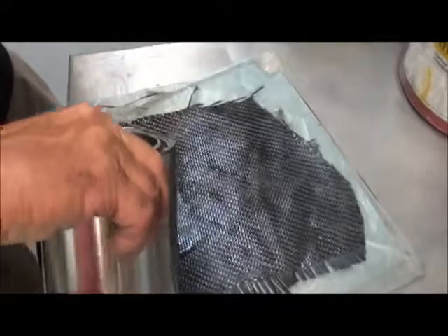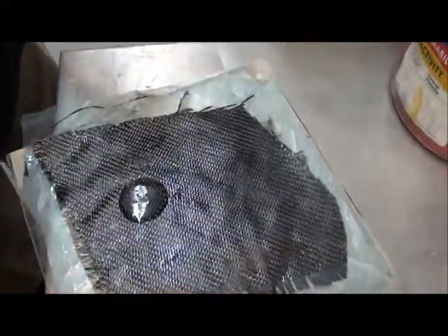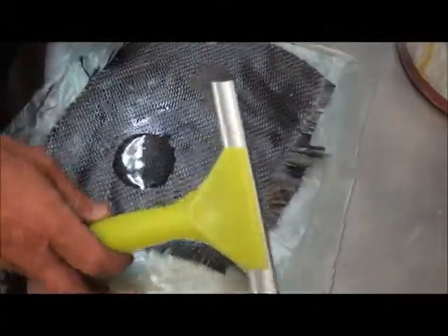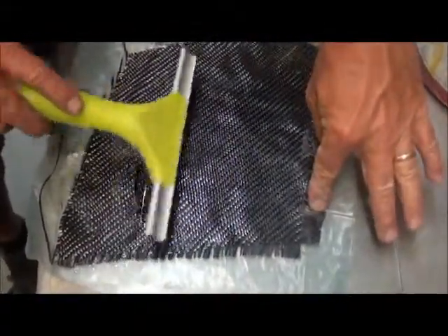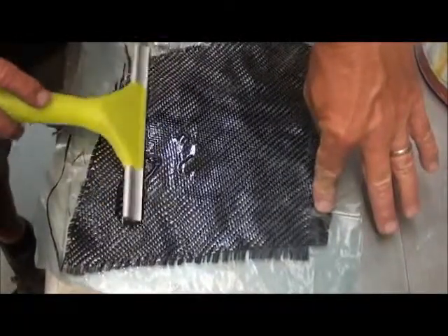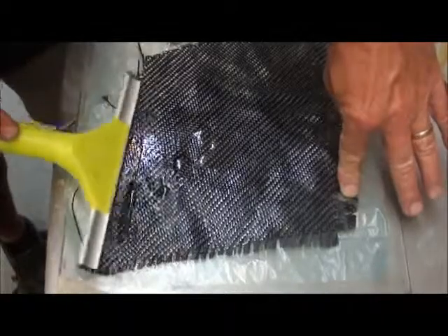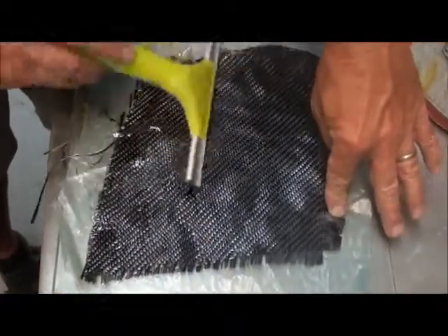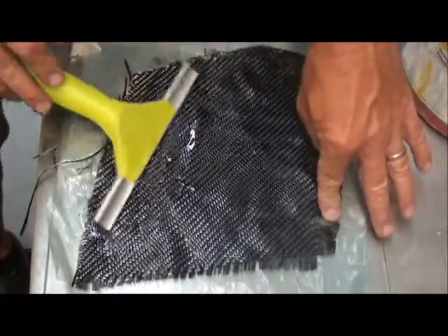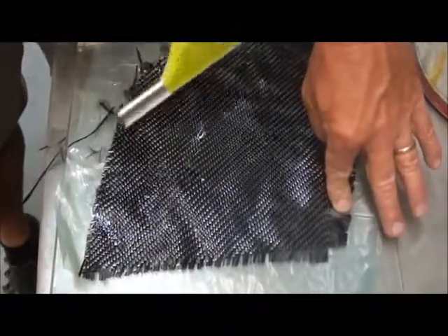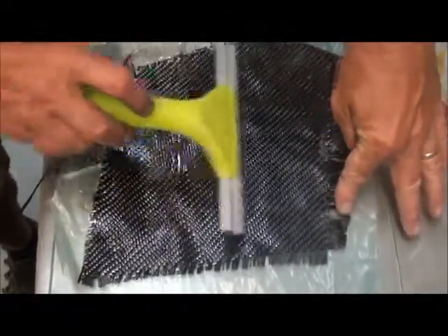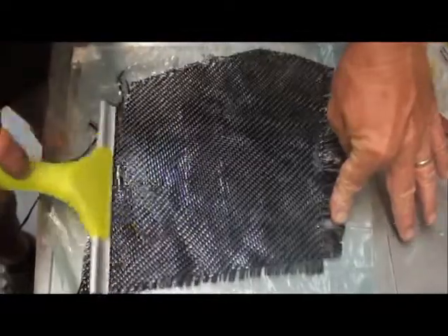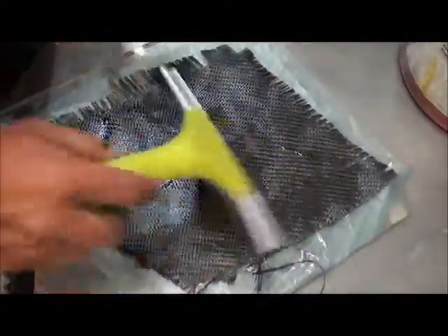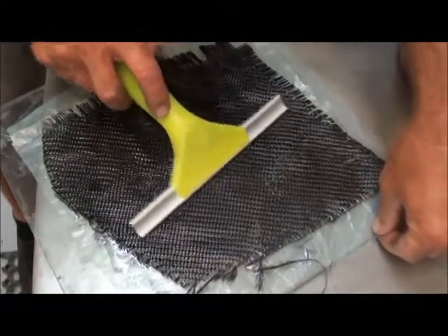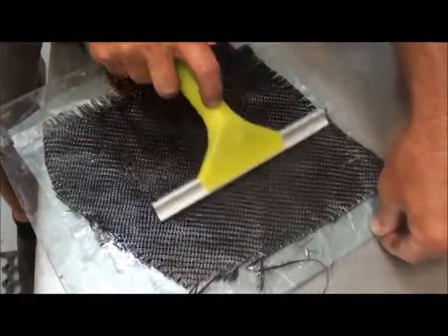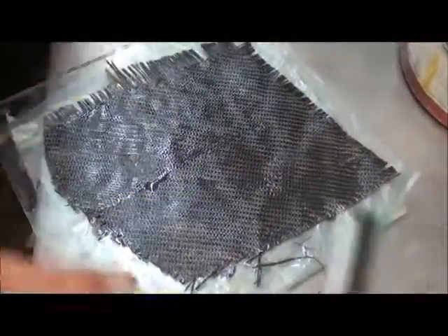We don't mind if it's a little resin rich because we're not concerned about weight for this experiment. But if you were concerned about weight, you would pre-weigh the composite sample and then measure out an amount of epoxy resin equivalent to roughly 50% in order to get what they refer to as a 50% resin content. 50% by weight of the cloth. And then that's all you would put onto it and work it in. But in our case, we're going to vacuum it off. In our case, we're just going to try to get a thoroughly saturated composite part just for the purpose of demonstrating the vacuum.